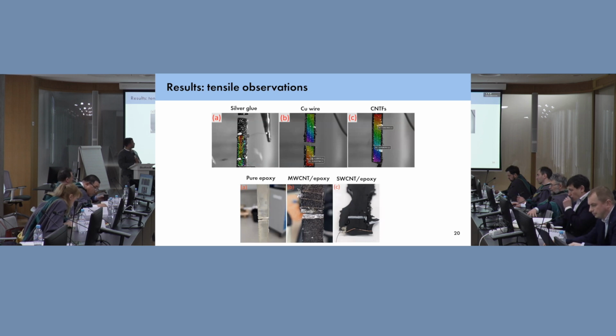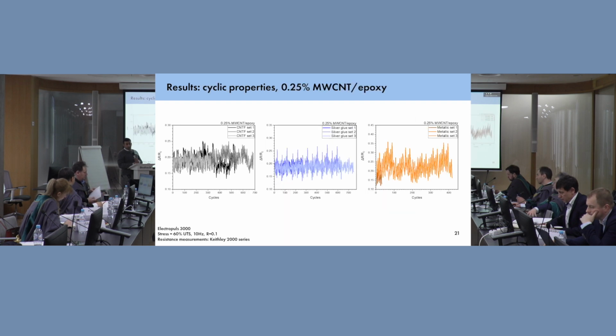For our Cu wire, which is image B on top, we start to see a clean crack right there. And for CNTFs, if you notice, you'll be able to see in this region a little fuzzy places. Our contacts did come off, but a failure did not happen in this location. And just to help illustrate it, we have images from different types of samples for multi-wall, single-wall nanocomposites, and pure epoxy. In all cases, we see failure take place right there. So we understood, okay, there is a problem with the traditional method when it comes to mechanical loading.